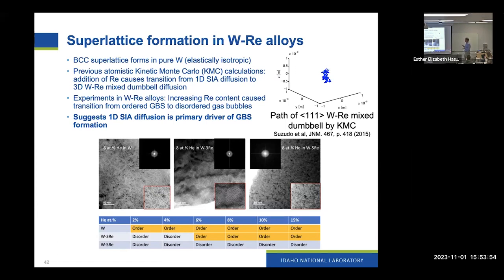And so there was some previous work that had been done that showed that as you add rhenium to tungsten, it causes a transition from 1D diffusion of the interstitials to 3D diffusion of mixed dumbbells. And so he designed an experiment just to add rhenium to varying concentrations to these samples. And he found that indeed, as he increased the rhenium concentration, we saw a transition from order to disorder. The amount of rhenium that was needed to do that was somewhat varying depending on the sample. But I think this is the best evidence to date that the 1D diffusion of self-interstitial atoms is really the primary driver of the formation of these gas bubble superlattices.